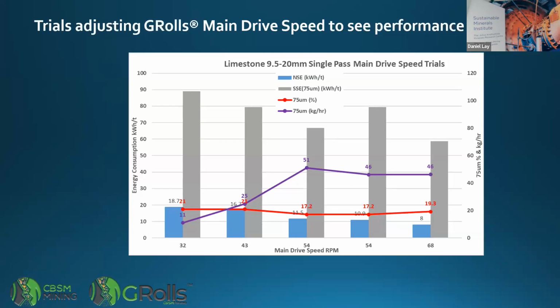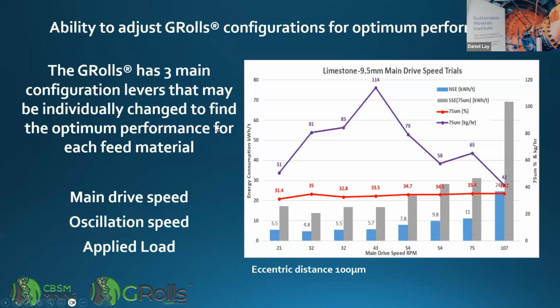When we went to the coarser material, we found that dropping the speed actually reduces your productivity and your energy, so you need slightly higher speeds because of the bigger materials. So what it suggests is that for every material you need to do a whole lot of tests to work out which is the sweet spot.